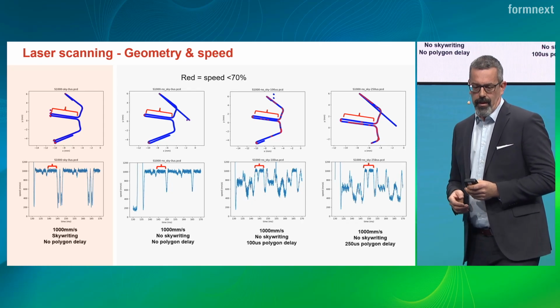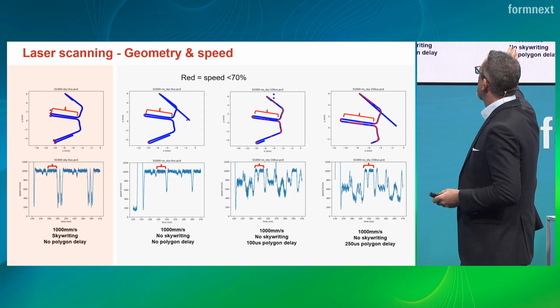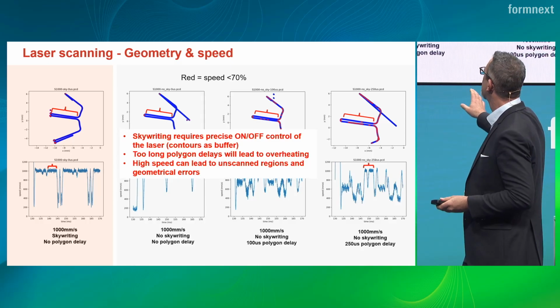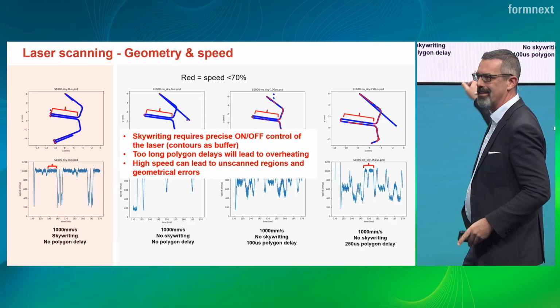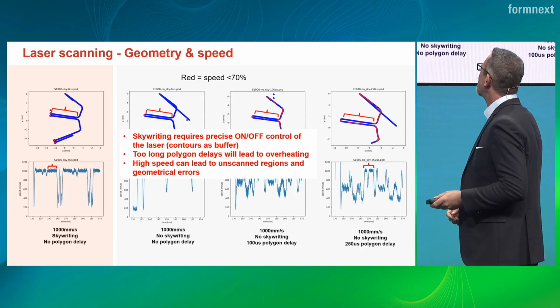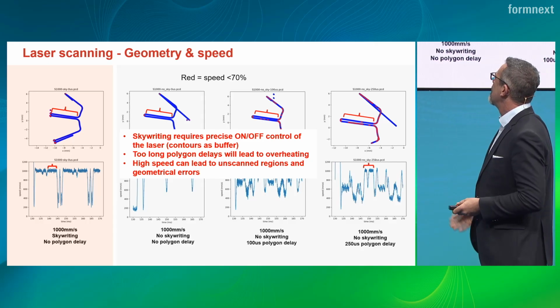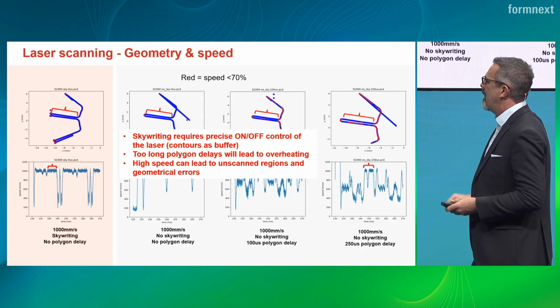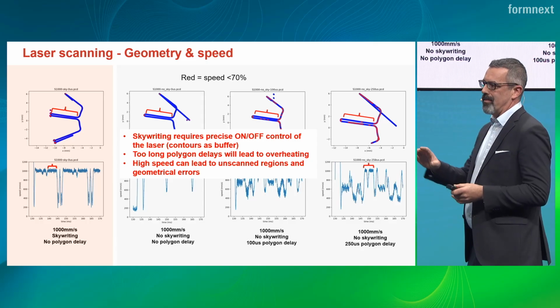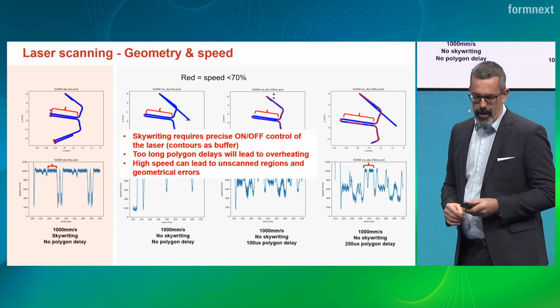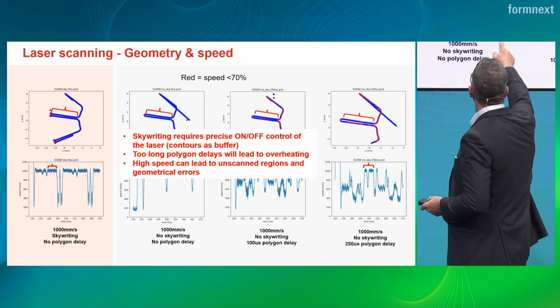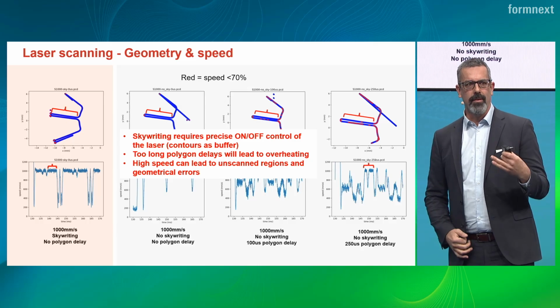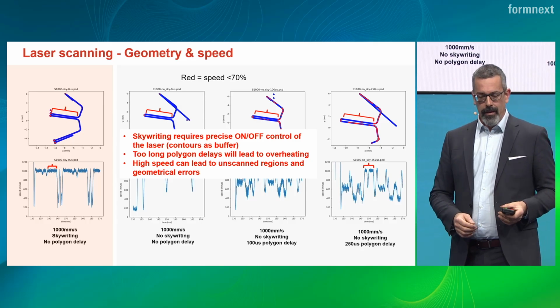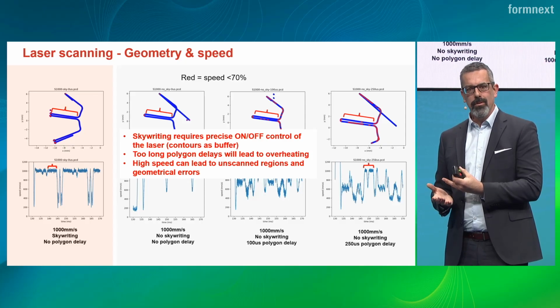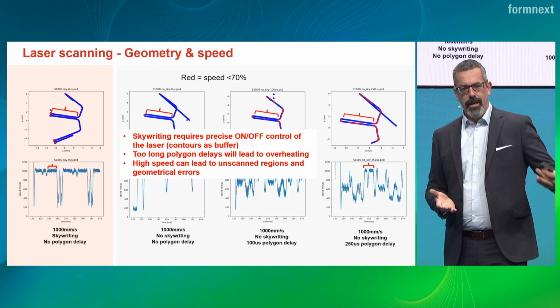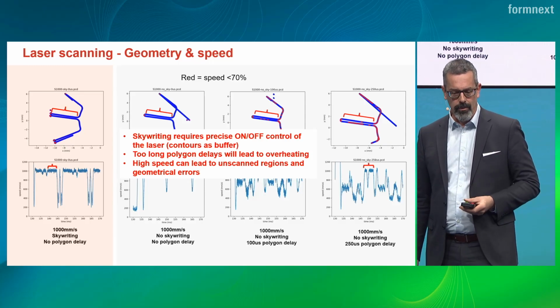Okay, here you see several situations. Now I'm puzzled because it looks different here than here. So, on the left-hand column you see a skywriting path. The blue is more or less the target speed that our laser reaches. If you see a red section, that means that the laser speed is below 70% of what you ordered from the scanner. And you know that power stays the same. So you add much more energy per length unit than you should actually do.